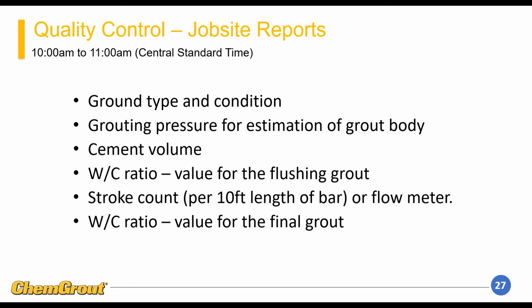you're going to have to do a test after you've flushed out all the flushing grout and are pumping in the structural grout. You're going to need to do a little sample at the top of the hole to assure that the structural grout is getting all the way back up to the top of the hole. One of the ways you can measure the amount of grout is to measure the stroke count of the pump that you're using, or use a mag flow meter to record the total volume that you injected in there. And then finally you'll do the water to cement ratio based on the mud balance, which will give you your final specific gravity number.